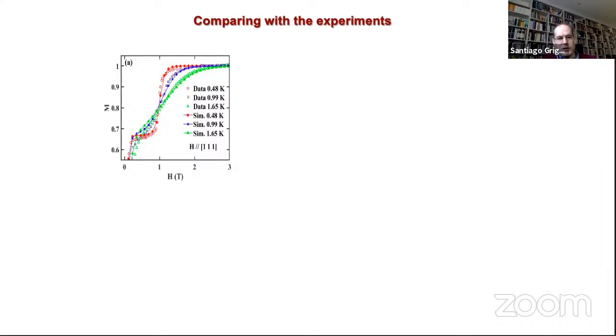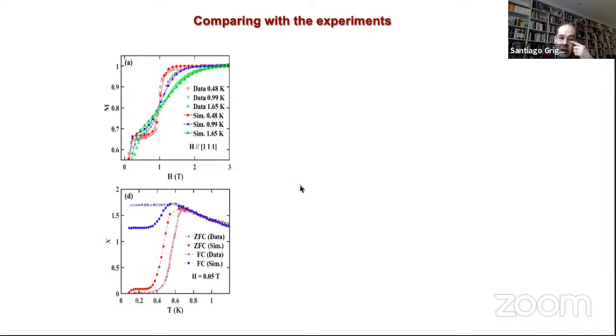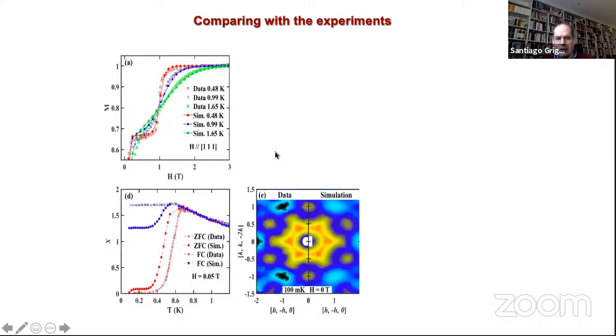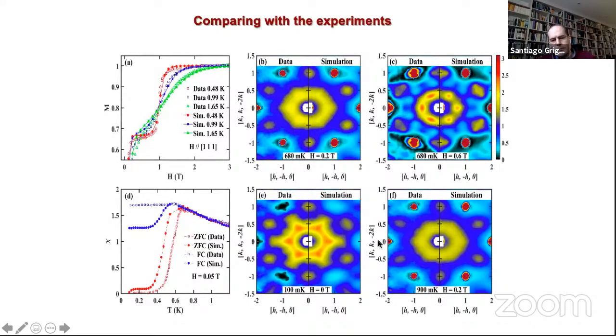So we did this fit at 0 field, and now, for example, we can compare what happens with the magnetization under a field between the data and the fit. And here you have neutron patterns for different fields. For example, this is for 0.2, 0.6. This is the original 0. And you see here that the left side is coming from the experiment, and the right side is the simulation, and you see that the fits are very good. So this is for 680 milli-K, this is for 900 milli-K, 0.2 Tesla.